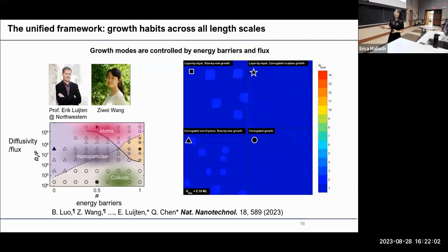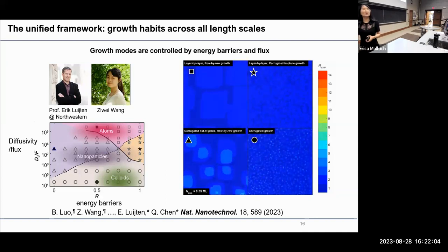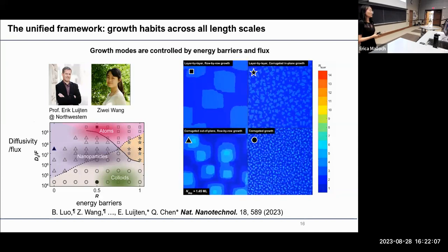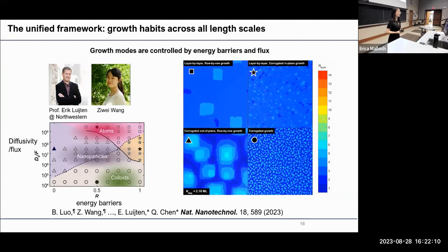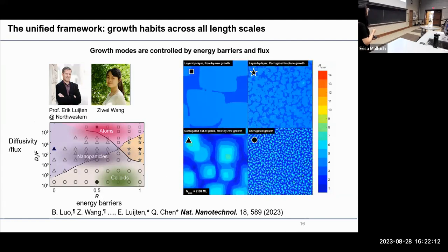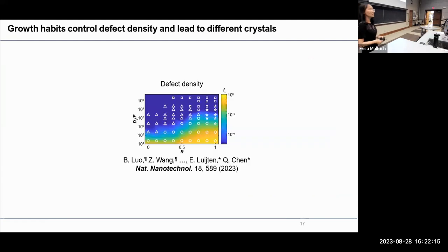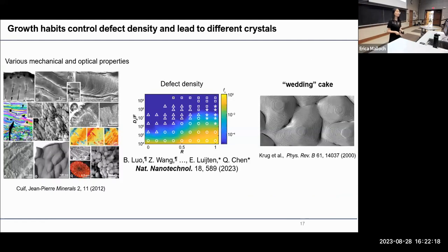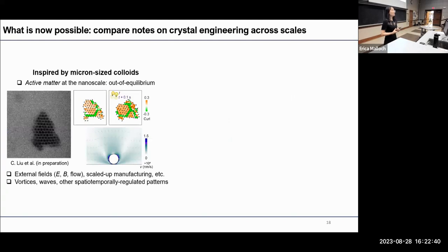And then for micron-sized colloids, they sit at the bottom. They correspond to corrugated growth in both 2 directions. So that's why you can see a lot of rough colloidal crystal in the literature. And the beauty is in nanoparticles, they can recover all the 4 growth modes. So that's why if you're using nanoparticles as a building block, you can have a huge library and huge tunability in terms of the crystal morphology, size, and shape, as well as the bulk defect density. With all those fundamental studies, this allows us to appreciate what are the similarities, also differences for building blocks of different sizes. And this can motivate us to start to